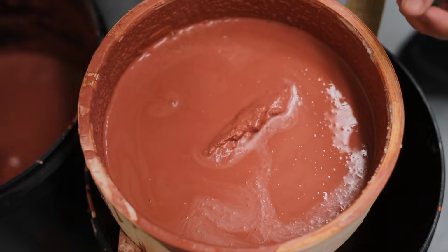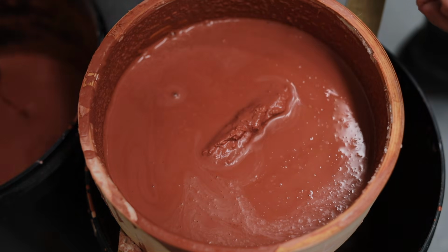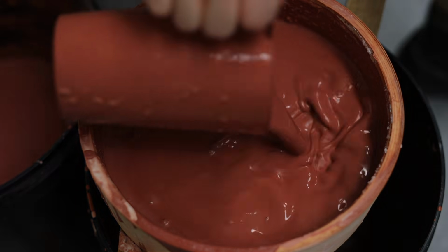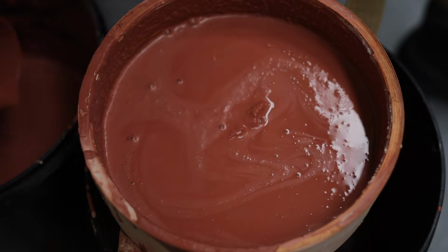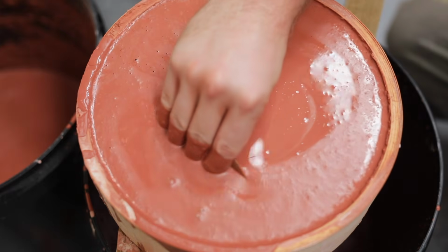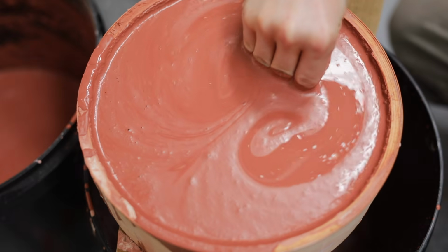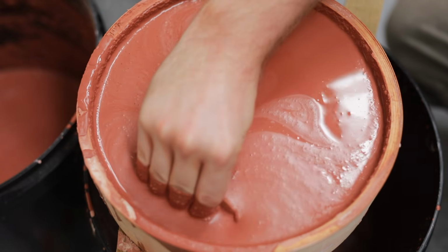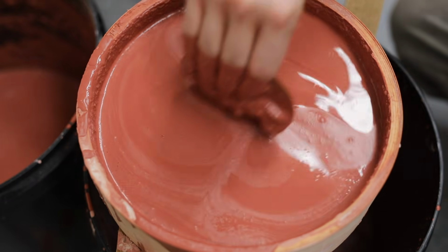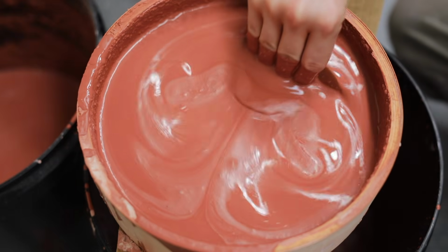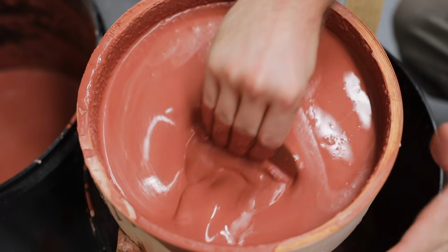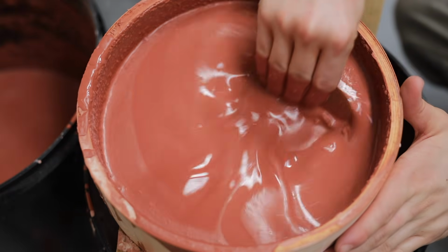I blitz this solution with my 5-gallon mixer, and then sieve all of it through an 80 mesh sieve. As the clay body of the pots is porous, when you dip a piece into the glaze, the water is absorbed into the clay body and it leaves a layer of these raw materials on the outside of the pot.